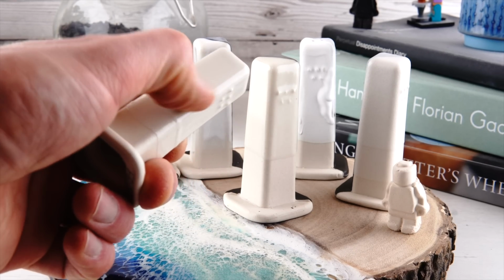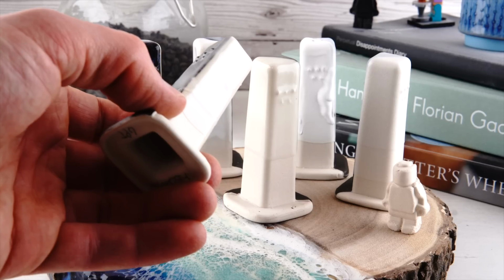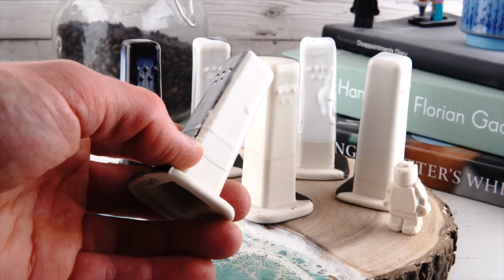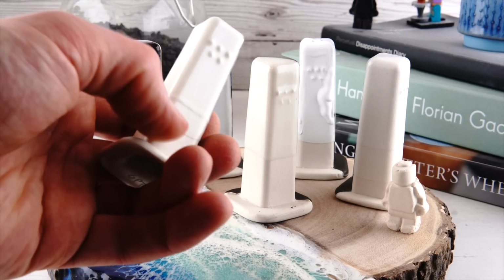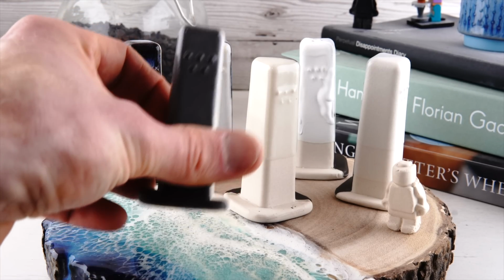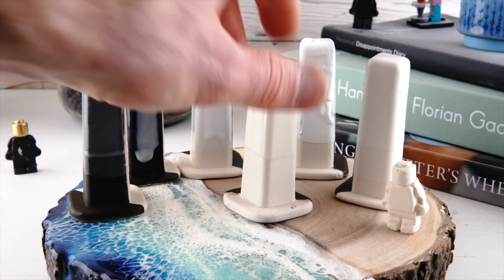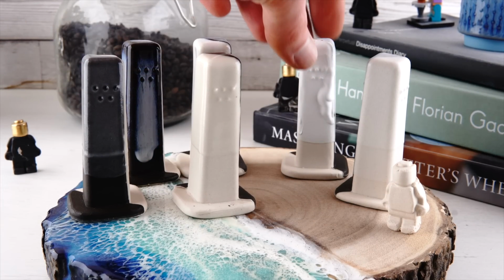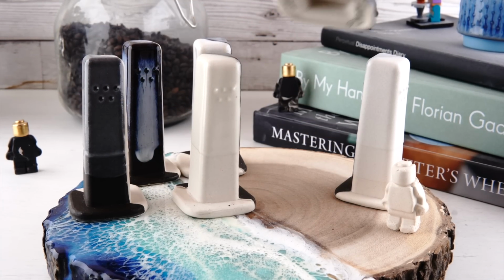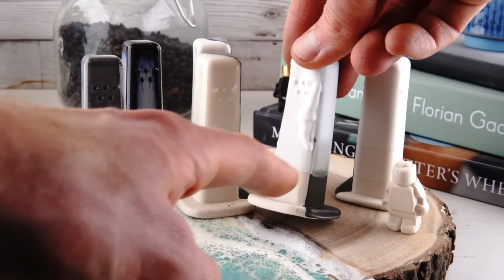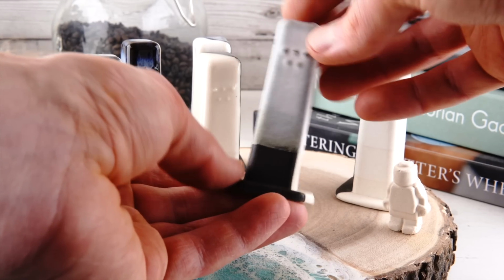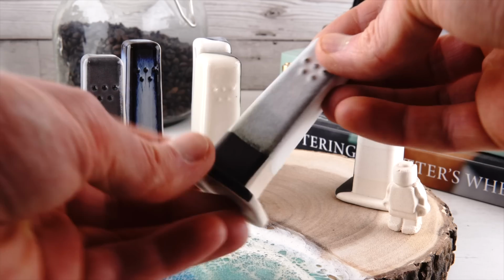This one, you've got slight gloss. You can see from the way the drip is preserved from the application, it's only just beginning to melt, and it's crazing, which I'm not surprised about. But that's the one with too much feldspar. And then you have this hideous monstrosity, which I don't know if it applied like that or if it's blistered. I'm not quite sure what it's done there, but that's the one with too much carbonate, so loads of calcium in it. Not at all a glossy cone 6 glaze.